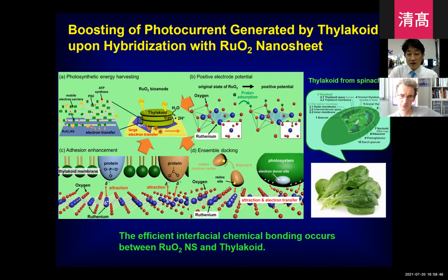Also, we applied ruthenium oxide to boost up the photocurrent generated from the thylakoid. Thylakoid is obtained from vegetables like spinach. Many people use thylakoid to induce photocurrent, but people immobilized thylakoid on the surface of a gold substrate, and there is limited electronic coupling. So to enhance the interfacial electronic coupling between the thylakoid and substrate, we introduced ruthenium oxide, because in the ruthenium oxide nanosheet there are many sites for cationic binding and anionic binding.